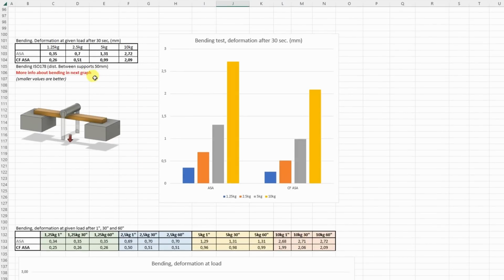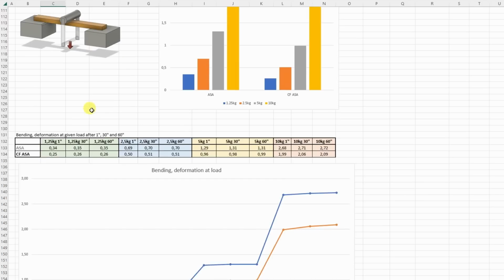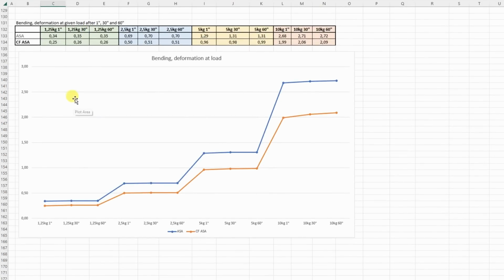And now that bending test. For me, this is the most important information. Let's see first this graph. These are the deformations after 30 seconds when I place 1.25, 2.5, 5 and 10 kilograms. And if we watch only this, Carbon Fiber ASA is better. Smaller values are better, less deformation. But let's see what happens if we watch the time too.